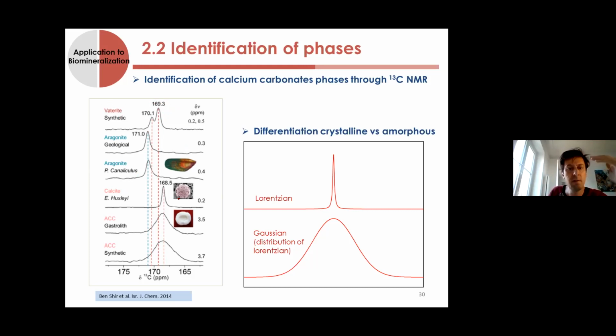And you see that in the case of different organisms, you can identify the mineral phase that is different in nacre, for instance, and different in coccolith. And you see that it corresponds quite well with the synthetic samples.